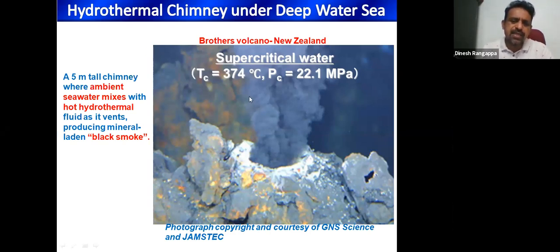Here you can see a volcano in New Zealand, beneath the sea. You can see about a 5-meter tall chimney where ambient seawater mixes with the volcanic vent. When the vent mixes with ambient seawater, you can see the formation of a mineral-laden black smoke, where hot fluid mixes with ambient seawater. It induces the supercritical condition for seawater, where the temperature is about 374 degrees and the pressure about 22 megapascal, which is the critical temperature and pressure for supercritical water. Beyond that, the water becomes a supercritical fluid. Under this condition, mineral formation occurs, and this condition was simulated in the lab, and we developed a